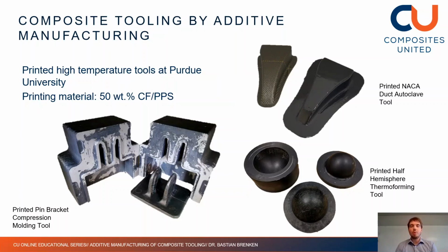And then we went even another step further and wanted to see, can we do compression molding? And you see on the lower left you can see the compression molding tool for a pin bracket that was also shown. So even compression molding with process pressures of up to 30 bars roughly, we were able to do, and we were able to use printed tools for that.